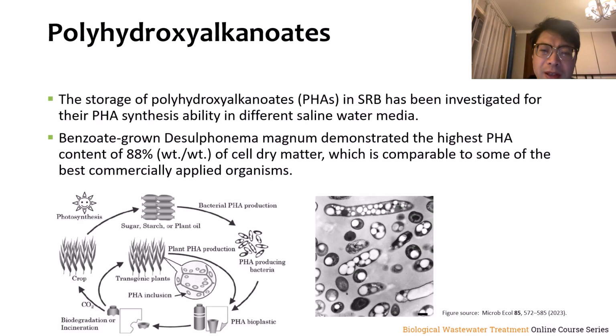Let's discuss an advancement in biotechnology regarding the synthesis and storage of polyhydroxyalkanoates, PHA in short, by sulfate-reducing bacteria in saline water environments. PHAs are biodegradable biopolymers and potential eco-friendly substitutes for petroleum-based plastics. Research indicates that certain SRB, especially when cultured in saline conditions with benzoate, can accumulate significant amounts of PHAs. For instance, Desulphonema magnum can achieve PHA content as high as 88% of cell dry matter, a figure competitive with the top commercial PHA producers.